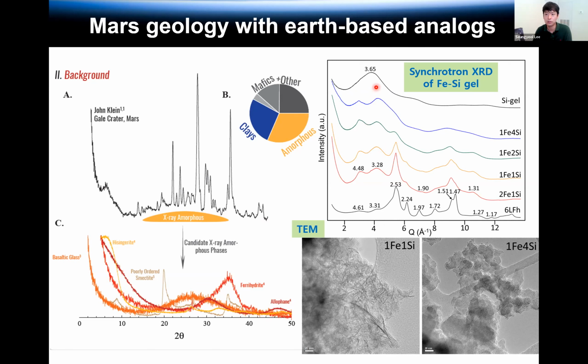So I made different iron silica ratios. This is silica and different chemical ratio iron silica gel, and this is ferrihydrite synchrotron XRD data. Actually, this pattern matches this area quite well. So I plan to do a more detailed study about the iron silica gel structure formation for understanding Mars geology. Actually, this is a very complicated process. So the XRD pattern also changes under TEM, the texture also changes. It's not simple, it's a very interesting topic for me.